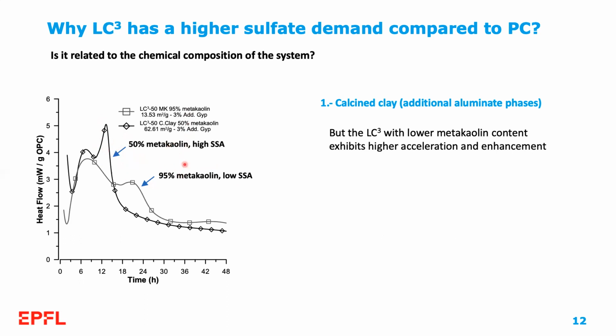The difference between the two clays is that the lowest grade clay, meaning lower metakaolin content, has a higher specific surface area compared to the higher metakaolin content system. And we can see that by the increased enhancement of the alite peak in the case of the 50% metakaolin system. So it appears that the acceleration of the aluminate reaction is more related to the filler effect contribution of the calcined clay rather than the alumina contribution of the material.